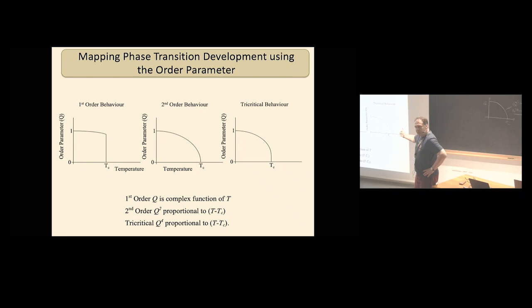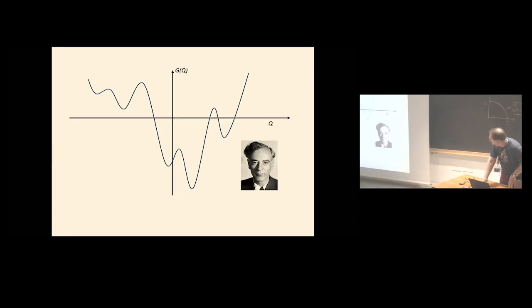This is genuinely equilibrium. So, you know, the fact that you move from a high symmetry state to a low symmetry state, and that there is some process by which the phase transition occurs. When you say process, you tend to think things developing over time. This is not anything to do with kinetics. This genuinely reflects the equilibrium value at each one of these temperatures as the thermodynamic environment is changing. There is a distinct equilibrium value for the order parameter. Okay, so it's not anything to do with kinetics, and I think that's important to feel comfortable with.